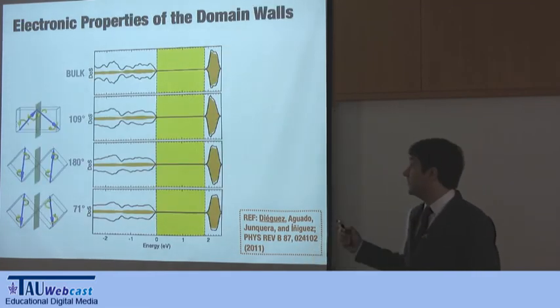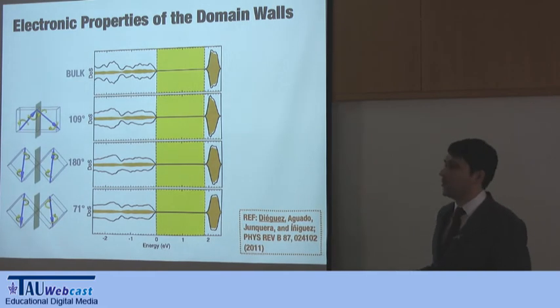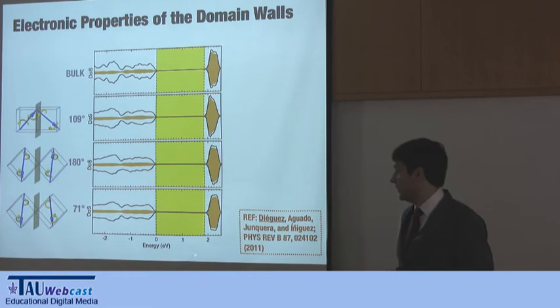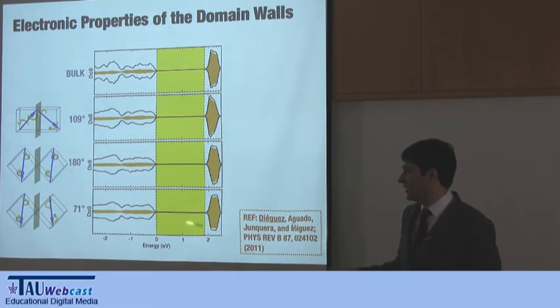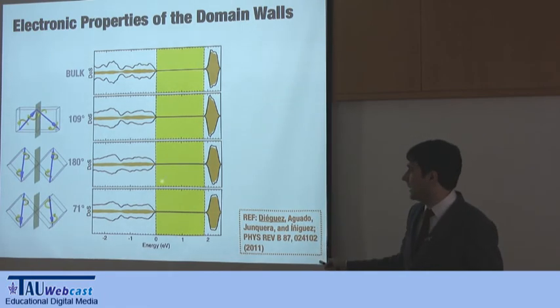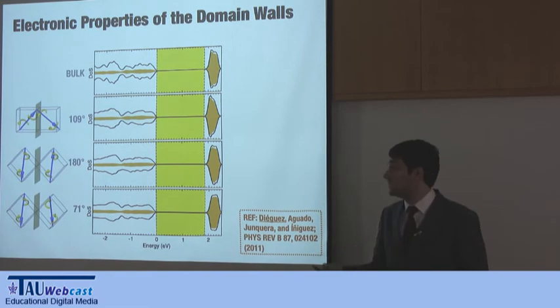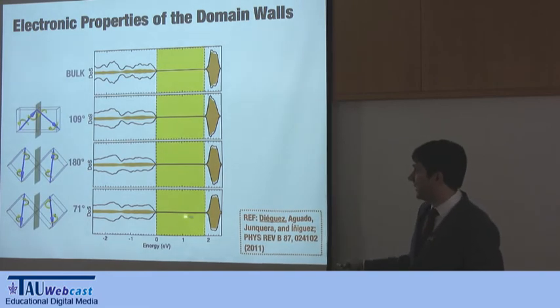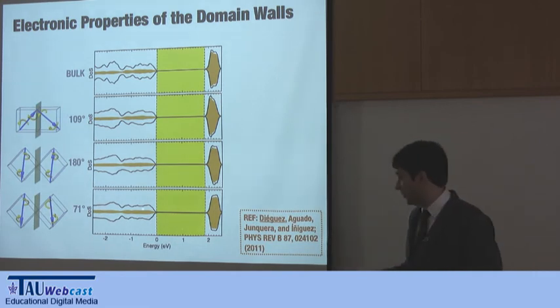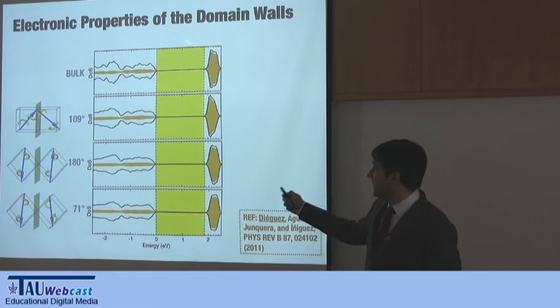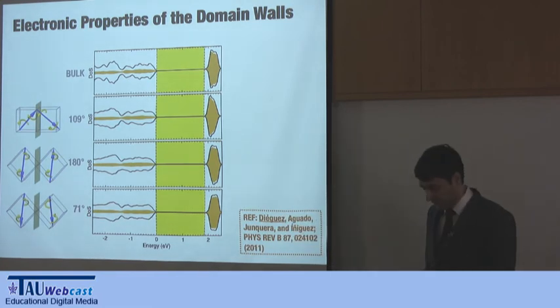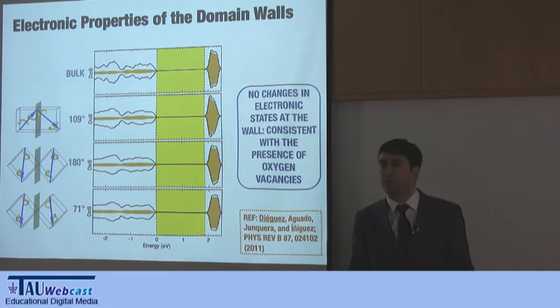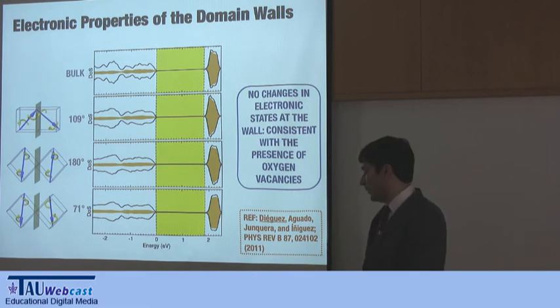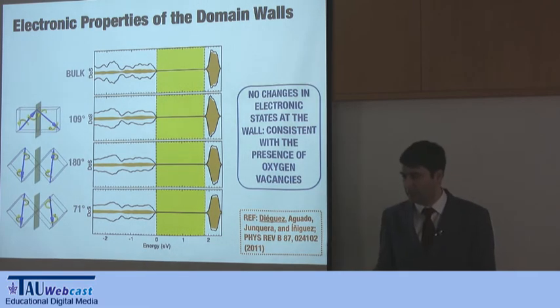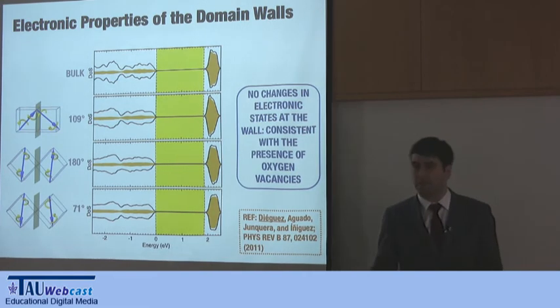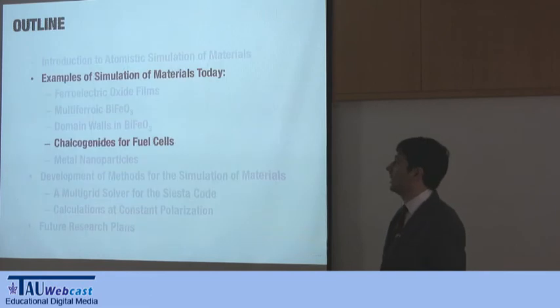we can look also at what is called the density of states. So how many states for the electrons are there for different values of the energy of these states. Up to a point, that is the Fermi level, you will fill those levels, and then you have your conduction band, and if there is a gap in between, you will have an insulator, because the electrons will not be able to move from here to there. What we see is that there is no change in this. So this goes against the interpretation that there is a rearrangement in the domain walls, and goes in favor of another interpretation of experiments that were done later, and that show that there are oxygen vacancies, and oxygen vacancies donate electron levels, and there you get your conduction.